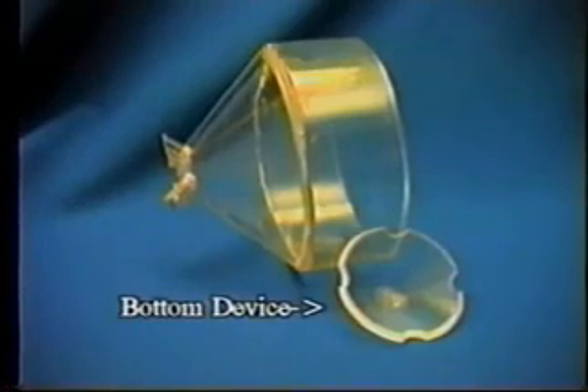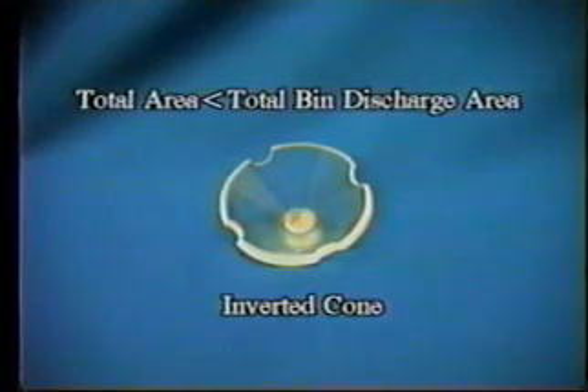First, to the right of the picture, is a bottom device referred to as an inverted cone. The cone has four half-circle openings located at equal distances around the circumference of the base of the cone. It's critical that the total area of these openings is less than the total area of the bin discharge opening. That way, sand flowing through these openings will exit without backing up and filling the chamber under the cone.